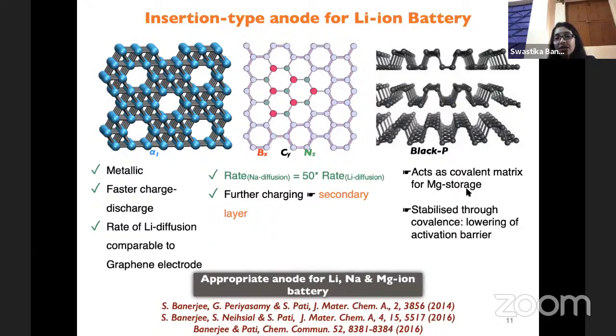Because magnesium is 2+ in charge, it's very hard to find a system which will store the magnesium with sufficiently low binding energy. Usually, whatever elements or layered systems we find have significantly high binding energy with magnesium. So our design principle was to get a covalent matrix that will help reduce the magnesium adhesion to the system. And we also thought of stabilizing the activation barrier through the covalence so that the overall diffusion barrier will be reduced. So it will allow fast diffusion for the magnesium through the system.